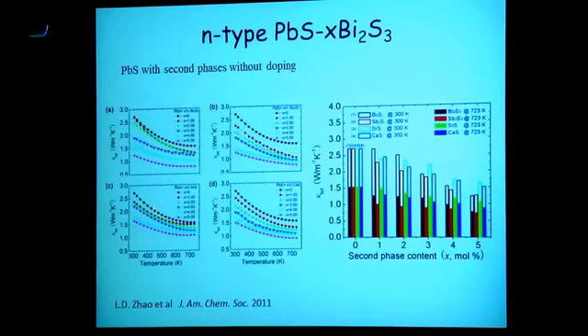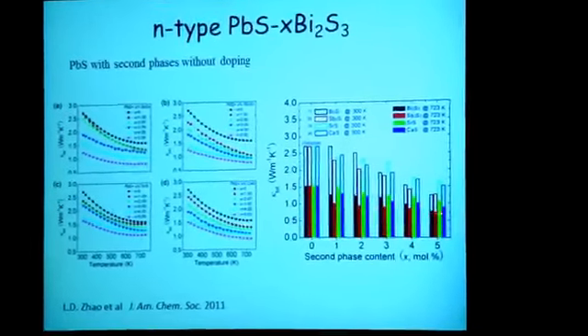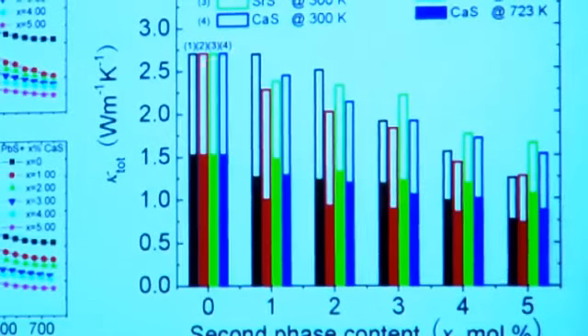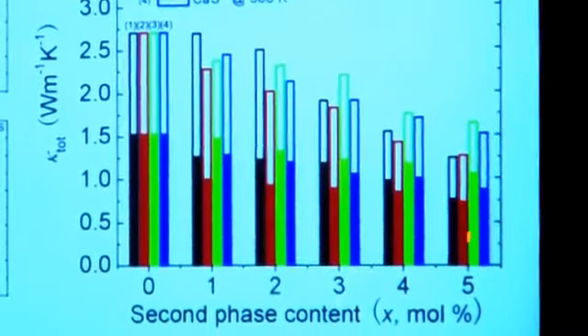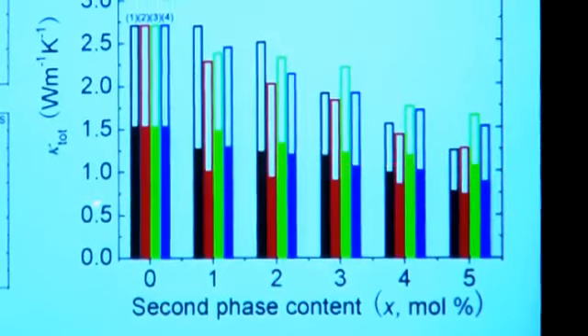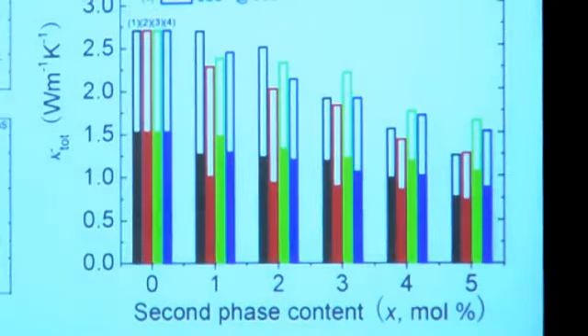And here, these are thermal conductivities. And essentially, we see a spectacular drop. The black data is the pure lead sulfide. And we add 1, 2, 3%, all the way to 5%, and we can drop it way down. That's a spectacular drop. Percentage-wise, actually, is better than lead telluride. So we can do this with bismuth sulfide. We can do it with antimony sulfide. We can do it with strontium sulfide, and we can do it with calcium sulfide. And these are the values we get. The solid lines are the values at high temperature. And you see these numbers are close, between 0.5 and 0.8. And the empty bars are the room temperature values. So what we are interested in is the solid bars, because these are the high temperature numbers. And these are very low for lead sulfide. Nobody has been able to decrease the thermal conductivity of lead sulfide that low.